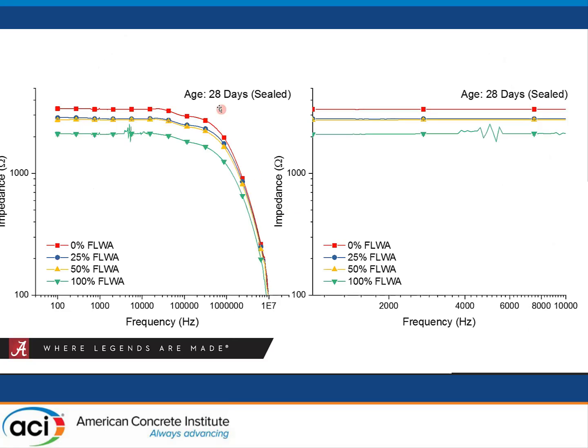Like if we look at this, our 28-day sealed, we see this in our 100% lightweight mixture. We don't see it in the others. And here's a zoomed in section. And remember, this line here is an average of 5 samples. And so we see this consistently sample to sample. And so we got this data and like, okay, we're obviously doing something wrong with the device. We probably selected the wrong setting or just messed up something.